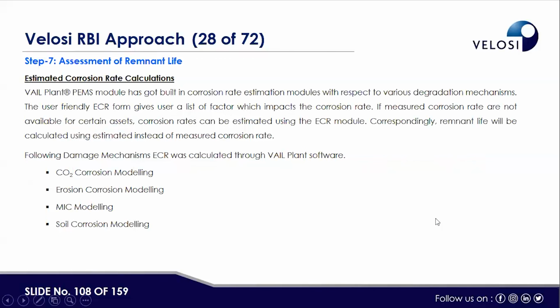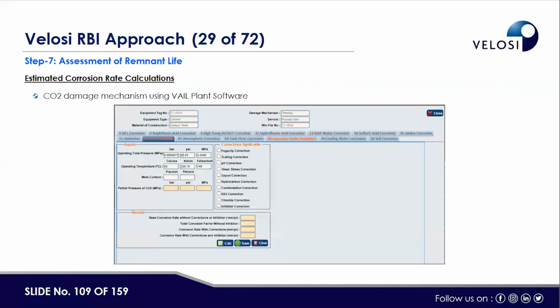Then for estimated corrosion rate, we use the software module, whether it is CO2 corrosion modeling, MIC modeling, or soil corrosion modeling. For this, we provide the parameters applicable to that particular equipment and try to estimate corrosion rates using VAIL-Plant software. This is for CO2, where the various damage mechanisms are here, and by applying inhibition correction, H2S correction, and chloride correction, these corrections can be applied and the damage mechanism can be assessed.